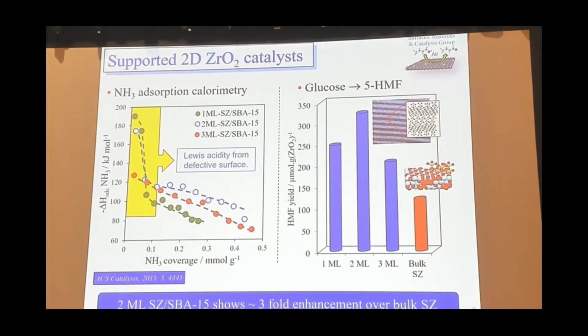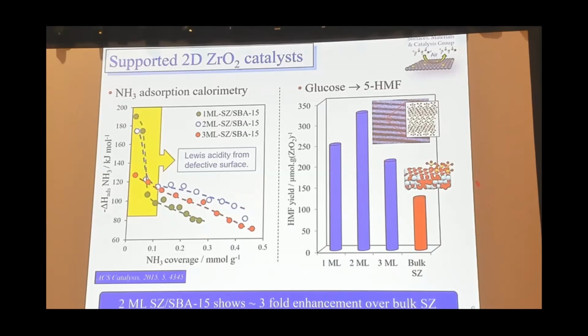So again, looking at glucose to HMF, this is the best bulk sulfate zirconia sample with the high coverage of sulfate, the best sort of HMF yield per gram of zirconia. If we look at the graphic systems, you can see that when we have a 2-layer film, then we end up with an overall 3-fold enhancement compared to what a bulk sample would be. So by dispersing the zirconia, we can improve the overall performance efficiency.